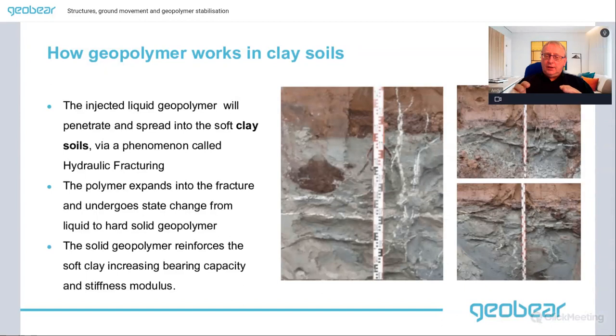Here we have a picture on the right-hand side of some geopolymer injected into a soft clay. And the white lines in the picture is the actual geopolymer, and the grey soil and the yellow soil is behind it. And on injection, the geopolymer essentially hydraulically fractures the clay, because we're talking soft clay. It hydraulically fractures it, and our geopolymer then migrates along that fracture, filling it in with geopolymer. And within that fracture, the liquid polymer undergoes a state change from liquid to hard solid polymer. The solid polymer reinforces the soft clay and increases the bearing capacity and the stiffness modulus.